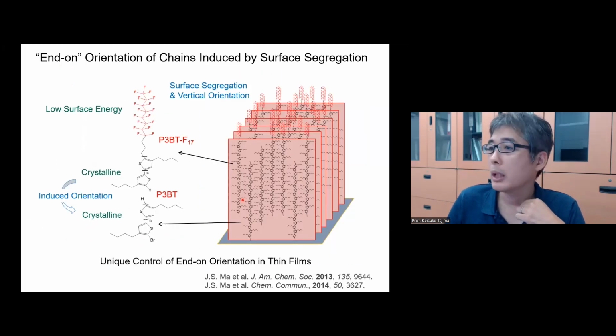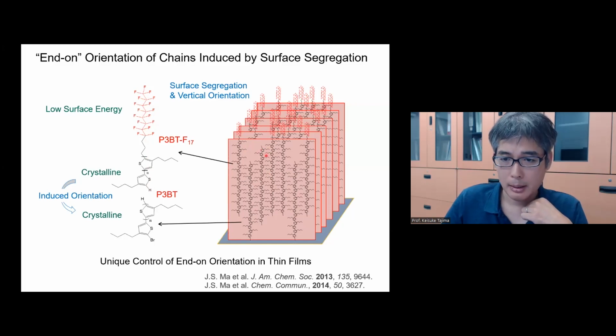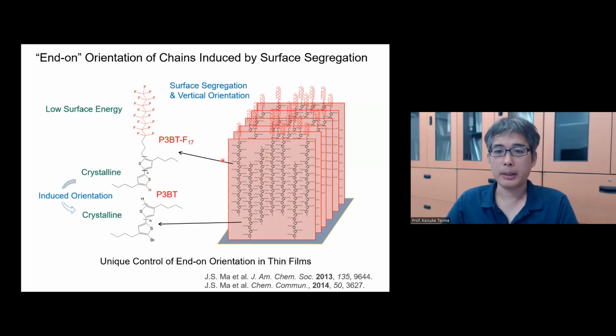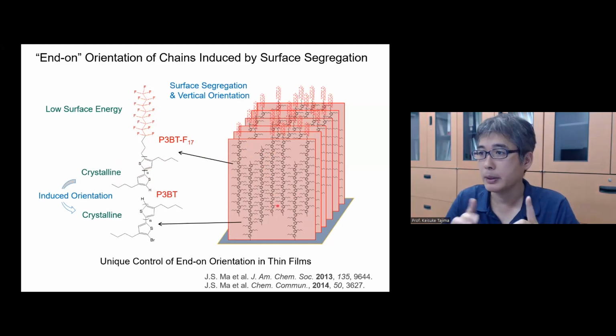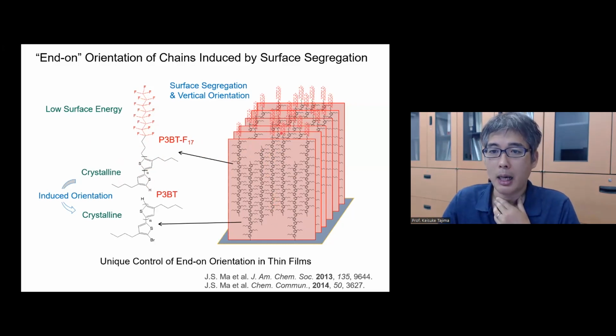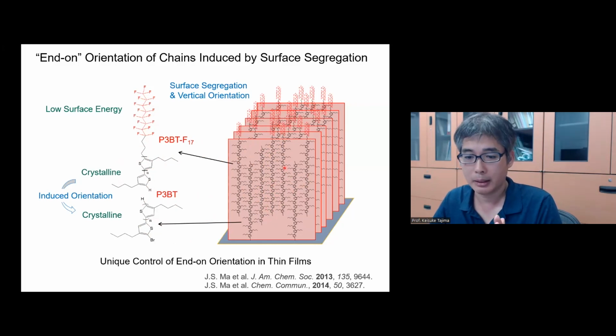And this is all about the molecular design. We can use the same principle of the low surface energy fluoride chain, but we change the design of the molecule. We attach this fluoride chain at the end of the polymer chain. In this case, this fluoride chain tends to segregate on the surface, and because of this packing, the main chain of this surfactant tends to align vertically. You can imagine that, right? If you have enough concentration at the surface and you mix these two together, this tends to crystallize inside the film, and the P3BT in the bulk also has the vertical orientation in the same film. That is what we found.